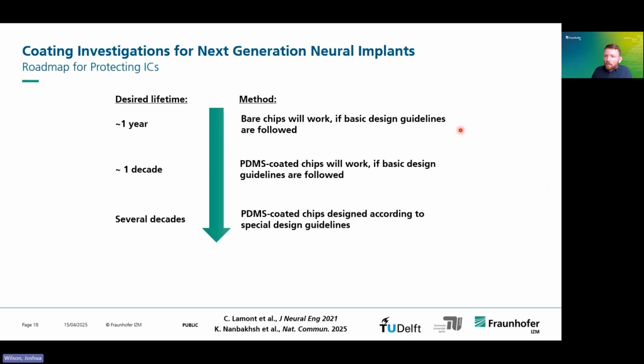So now that we know this, we can propose effectively a roadmap for protecting these ICs. Dependent on what lifetime you desire, if you only care about having your device in the body for 1 year, then okay, a bare chip will work. And if you adhere to some basic design guidelines, then you will be fine. If you want to go up to a decade, then you introduce this PDMS silicone coating, then you should be fine there as well.